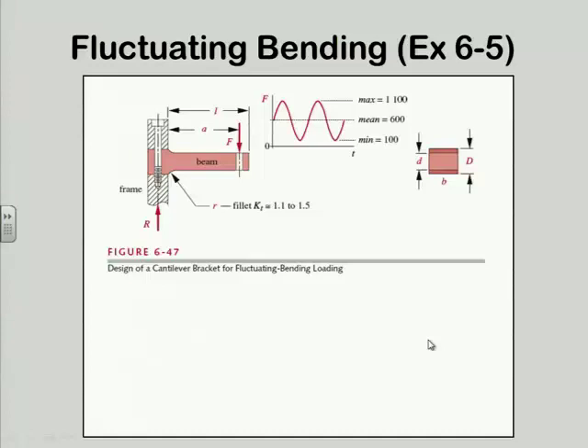So this is the example 6.5, which is building upon 6.4. And I walked you through 6.4 the other day, where 6.4 dealt with fully reversed stress on this same part. So now I've changed the loading conditions for the part to a fluctuating stress. And so I have a maximum of 1,100 pounds, minimum of 100, and mean of 600. I think it's pounds. Could be newtons.